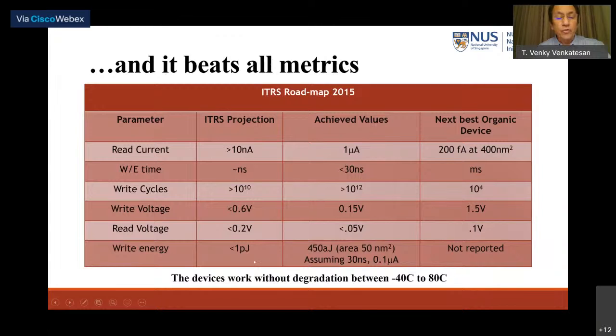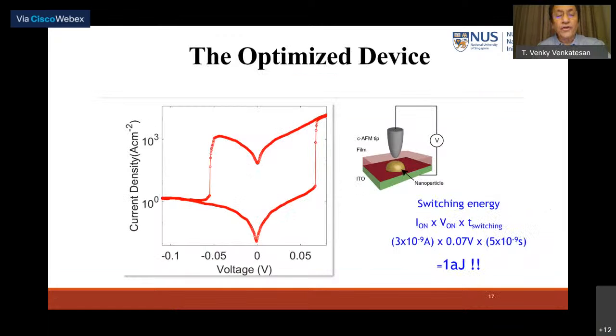And it should be less than 1 picojoule switching energy or writing energy. And here, in this particular device, it is 450 attojoules. But I'll show you a better device here. This is the device which switches on at about 70 millivolts with an on-off ratio of 1000. And with the conducting AFM tip, the switching energy that we see is 1 attojoule. To my knowledge, I don't know of any room temperature device, a switch with an on-off ratio of 1000 with this kind of a switching energy of 1 attojoule. I mean, this beats the nearest competition by almost 3 orders of magnitude. So indeed, I feel this is going to truly revolutionize memory technology.